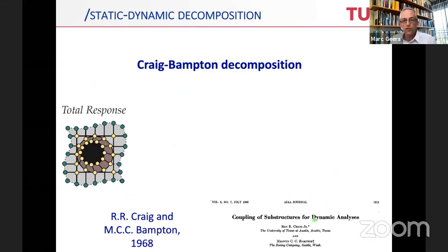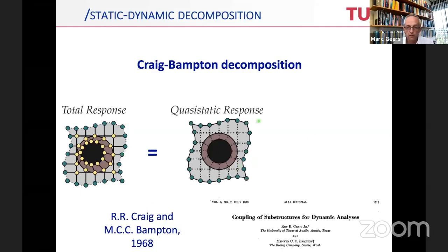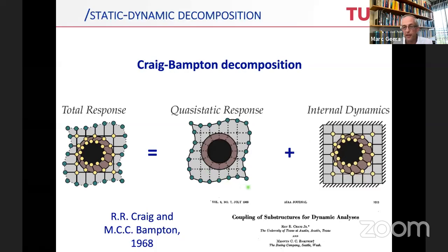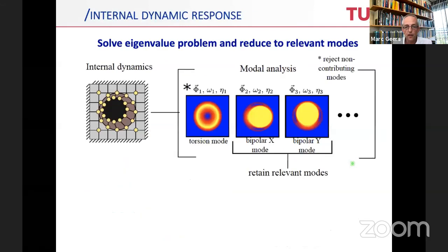Now, the advantage of using the linearity is that we can do a static dynamic decomposition, which is well known in dynamics as the Craig-Bampton decomposition. This goes back to 1968, which tells us that the total response can be seen as a superposition of the quasi-static response plus the internal dynamics. And this is exactly what we're going to do. We're going to make the split. And for the internal dynamics, we can look at the vibrational eigenmodes of the material to quantify this quantity. So for that problem, of course, you solve the eigenvalue problem.